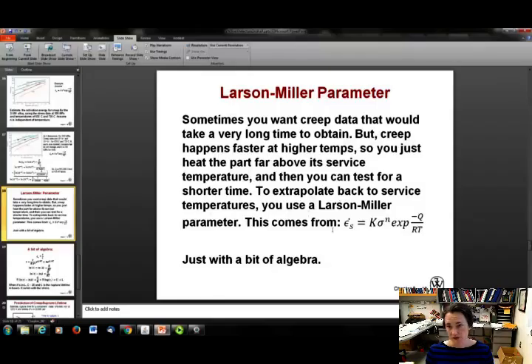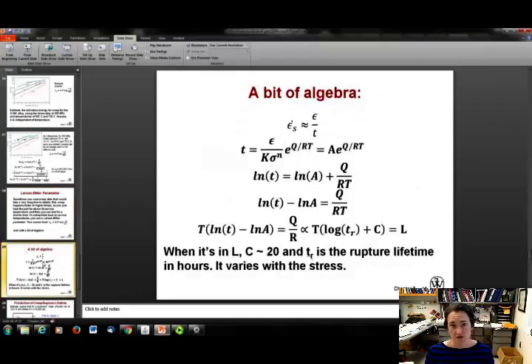Now, your Larson-Miller parameter just comes from the same old equation that we've been using. This creep rate is equal to K sigma to the N e to the minus Q over RT, and you just apply a bit of algebra to it. So here's that bit of algebra. If you remember that your creep rate is just your creep strain over a time t, then you can rewrite your equation to look like this, so that your time is equal to your strain over K sigma to the N times e to the Q over RT. So basically I just flipped the equation and multiplied through by my strain. Now I'm taking all this stuff out front because I don't really care too much about it. I'm just going to call it A for some constant, right?